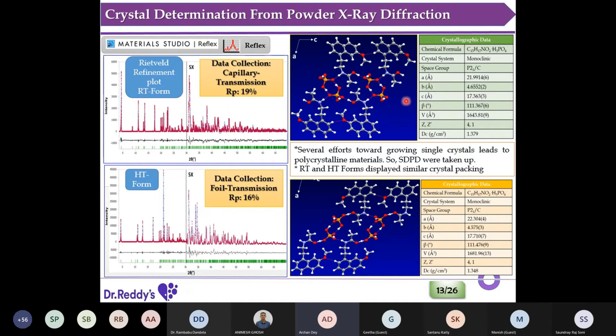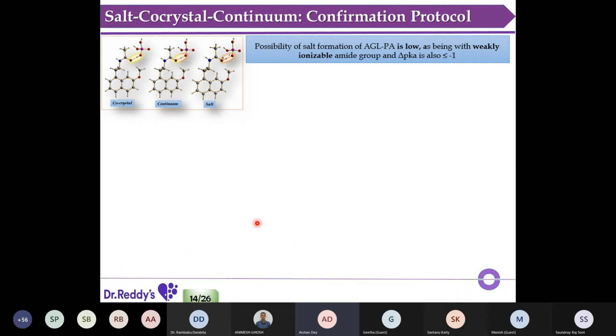If you can see, we got mostly similar cell dimensions and crystal structures. In a larger view, it looks like the same structure. I'll discuss in detail afterwards. There are differences. And after refinement we got reasonable R factors. That helps us understand that yes, the cell dimension is quite right, but you are still not 100% certain about the atomic positions, especially the hydrogen atom positions, because your hydrogen position was fixed manually. And all we know, to talk about whether it's a co-crystal or salt, we have to have the correct atomic position of the hydrogen atom. So towards this, we have worked further.